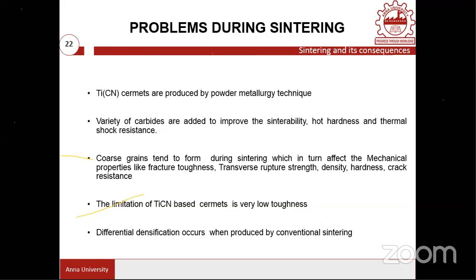During this long duration, sometimes there would be evaporation or removal of nitrogen. That's one problem with the conventional powder metallurgy route for TiCN, where the nitrogen will be partially evaporated. And also, since it is kept at high temperature for a longer duration, there would be obvious grain growth. So coarse grains tend to form during sintering. The TiCN tries to diffuse with other particles and make a bigger grain. That is a problem, as it will affect the mechanical properties: hardness, toughness, and rupture strength. Also the limitation is very poor fracture toughness because of the sintering.